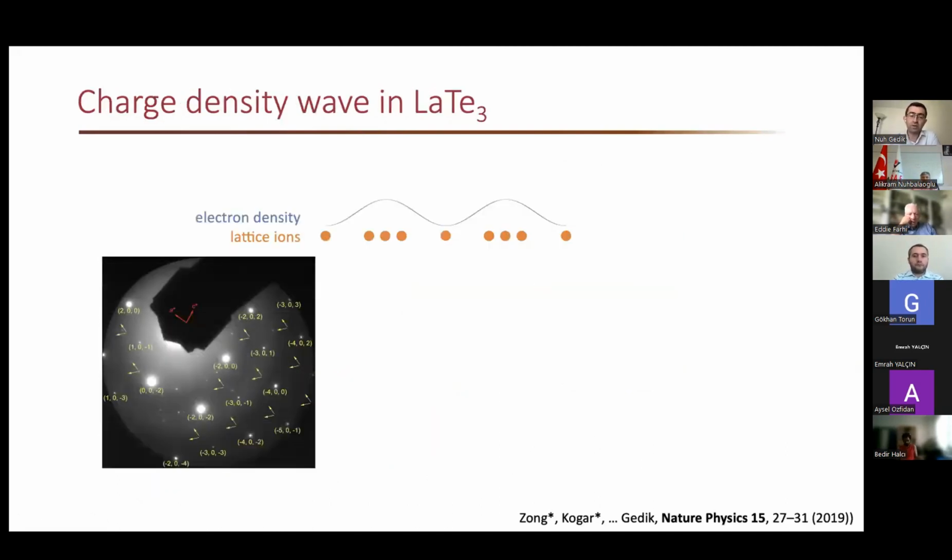So first, I just want to show you the static. This is a static electron diffraction pattern obtained in our chamber. Our direct electron beam is hitting here. It's too bright, so we put this ugly beam block here to block the direct electron beam. The bright spots that you see are our Bragg spots. Each one corresponds to an atomic plane. We can label them. And you can see there are tiny spots in between the Bragg spots. That is there because of this extra modulation. So we have a very good handle on the order parameter of this phase.